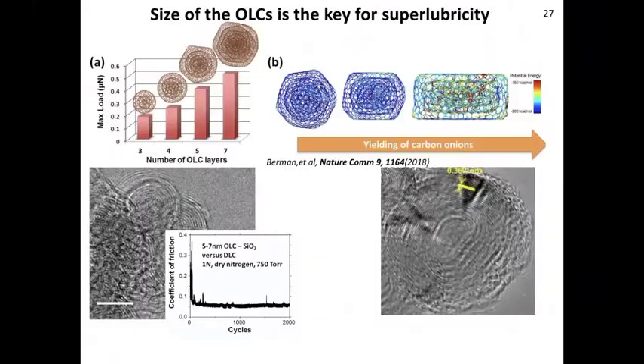With that, we started thinking, why would we need such a complicated process for creating this system? Why not just take small onion-like carbon materials, which you can purchase from vendors? The problem is that with these OLCs, you're usually limited in size to only approximately 10 nanometers. The way they are produced is by amorphizing the diamond nanoparticles directly and creating these larger shells. When we looked at them, they didn't really provide the superlubricity regime. The friction was in the higher regime. The major difference was that in that case, the onion-like carbon structures were small. In our case, they were really big. Why was it happening? Because now we have these agglomerates of diamond combined together and reconstructing to create more favorable conditions.